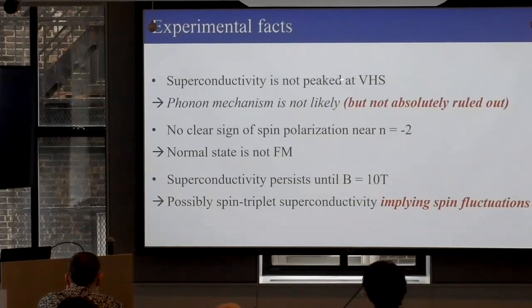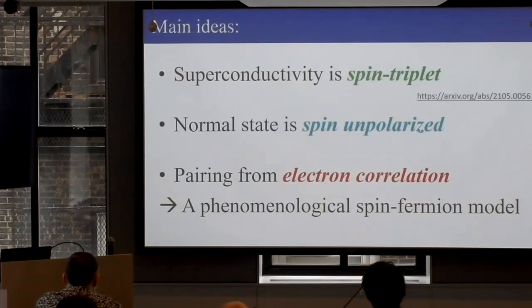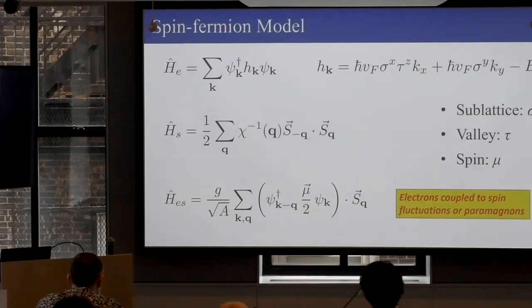So Pablo was triumphant. He said, it cannot be phonons, Sankar. He was really, really happy. So we did the calculation. I'm going to show you the result. The main idea: superconductivity is spin triplet here, and the normal state is still non-polarized. Pairing is from electron correlation, but we cannot do the kind of Hubbard model calculation that Andy was already doing. I'm not being modest, we do not have big enough computers, and we don't have the skill. So we did a phenomenological spin fermion model. Here we invoke that there are some spin fluctuations which give rise to superconductivity, some kind of paramagnons. Since there is a ferromagnetic state nearby, it's not an absurd thing, but it's a phenomenological model.